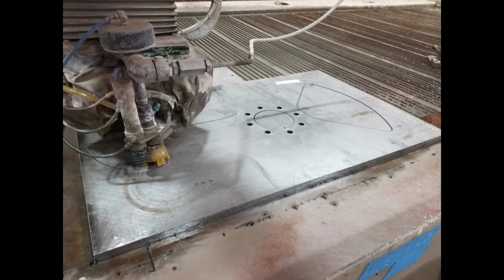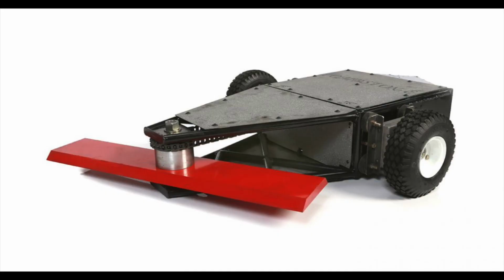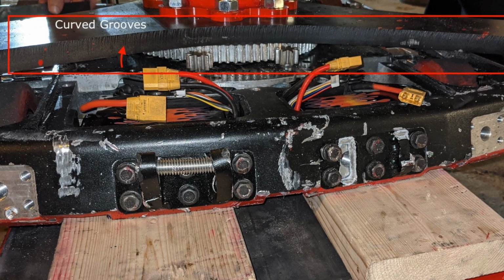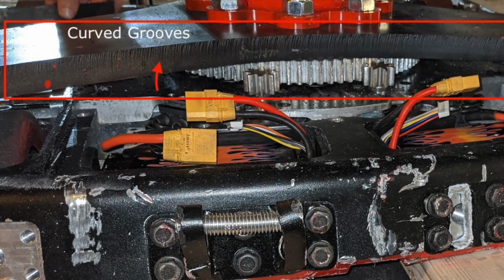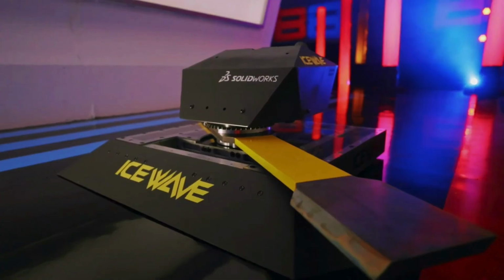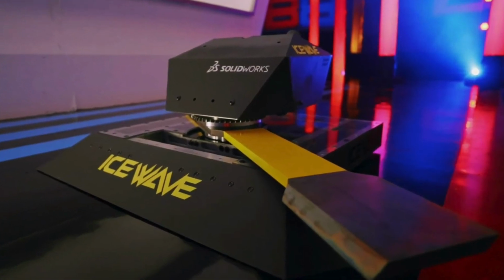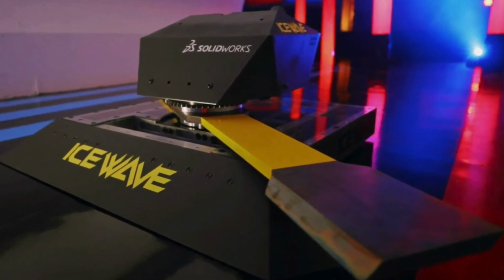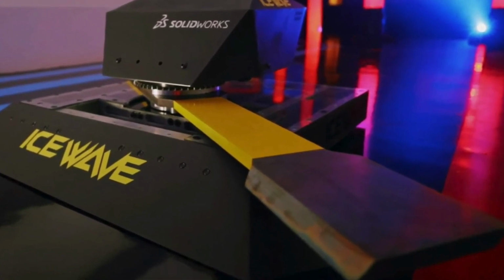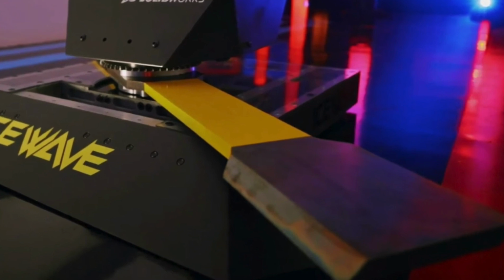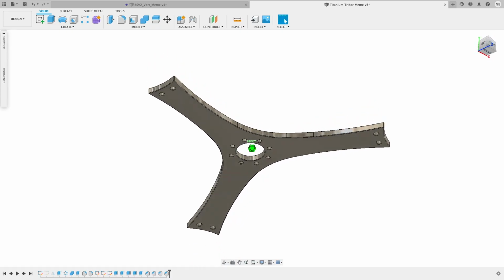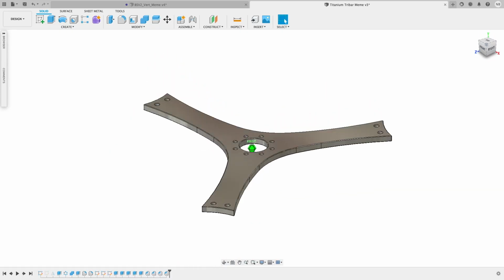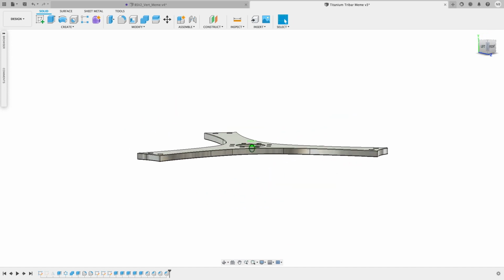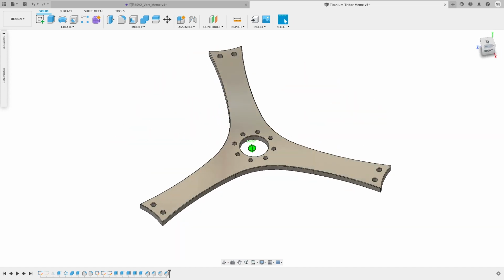These weapons were also water jet cut, in contrast to bots like Tombstone and Icewave whose bars were machined. Water jets can leave surface imperfections which might have been starting points for cracks. Machined bars have a much smoother edge surface, which could help explain why Icewave has such a good track record for bar durability despite having a longer, thinner weapon than ours. Unfortunately, we don't quite have the budget for a fully machined S7 tri-bar. The water jet one was expensive enough.